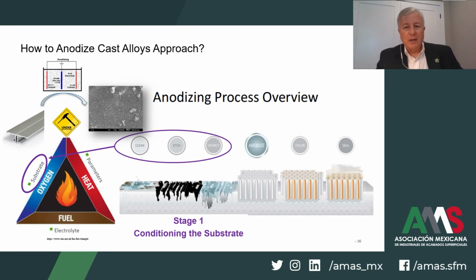So how to anodize cast alloys successfully? Well, the answer comes in 2 stages. The first stage is to re-engineer the thinking and the application of the cleaning and preparation of the cast alloy substrates. It's very important to avoid creating complex smuts that are difficult to remove from the surface. The fact that the formation of the anodic oxide dissolves aluminum, but also grows dimensionally into the aluminum, must be an important consideration for the final roughness specification or the brightness specification of the coating itself. This is why we've developed surface leveling and brightening components, but these are also reasons why there are many options for the cleaning and the preparation of cast alloys prior to anodizing successfully.